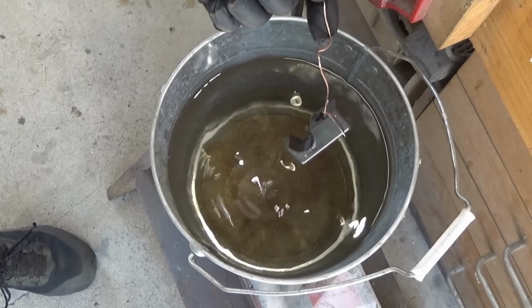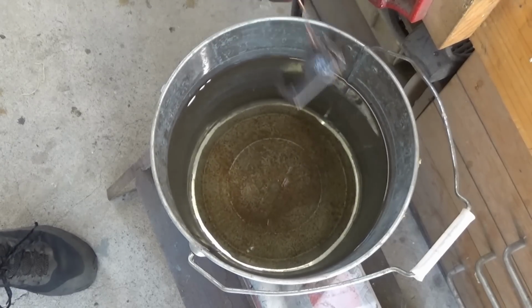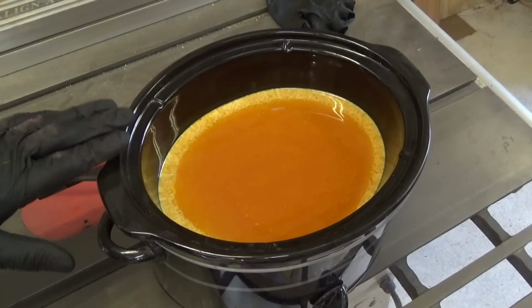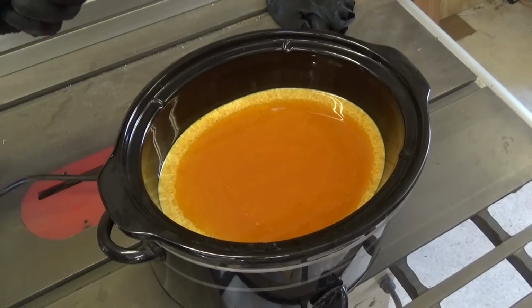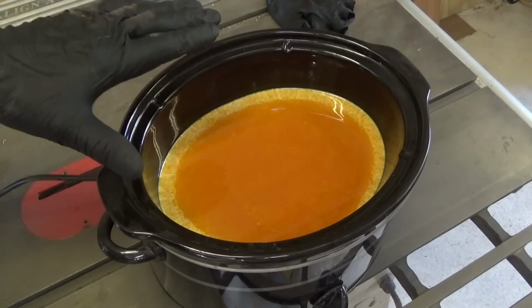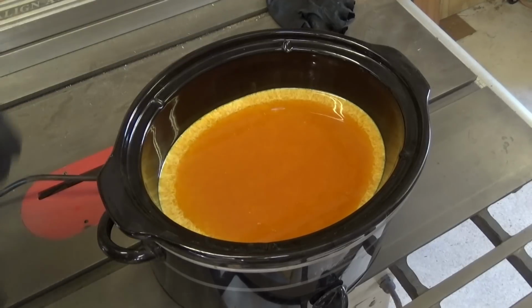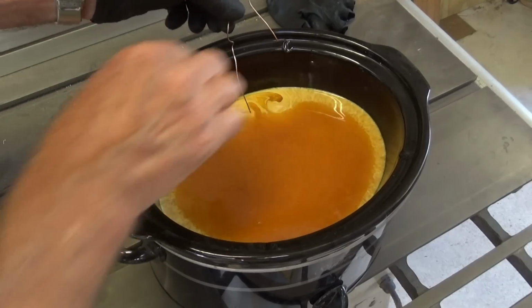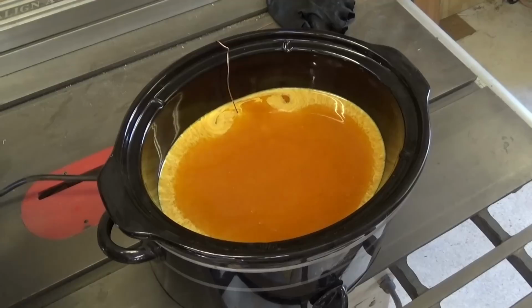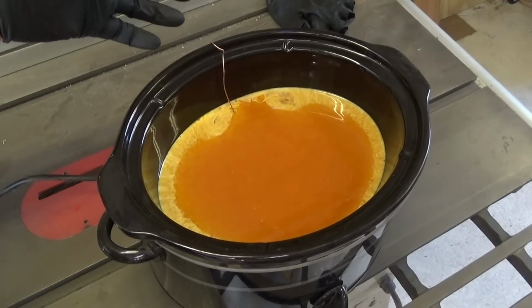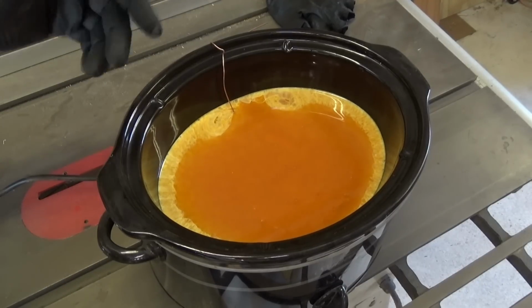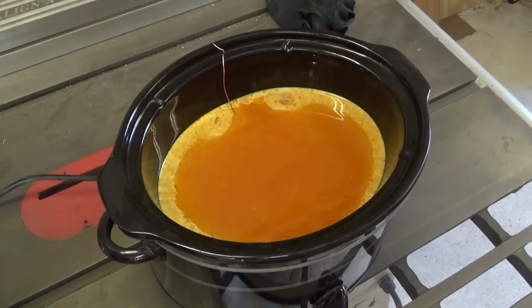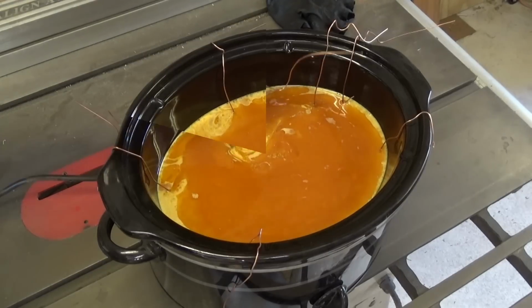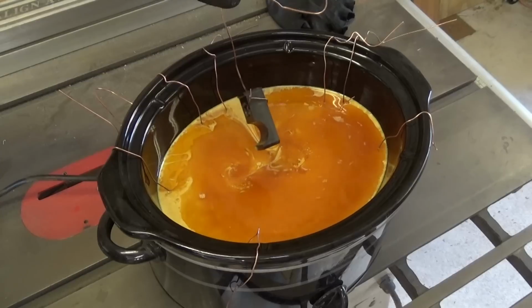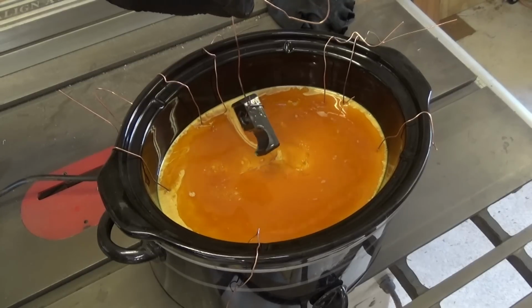Okay, that's rinsed clean. Now it goes into the hot oil. This is called a dry touch oil. It's just soluble oil based on water, and it's heated up to about 50 to 60 degrees C. And these parts are just sitting there for about, I don't know, like 10 minutes. Probably just dunking them for a couple of minutes would be fine. I'll probably leave it in there until the whole batch of parts is done. Okay, they're done. Just going to hang these up now to dry overnight.